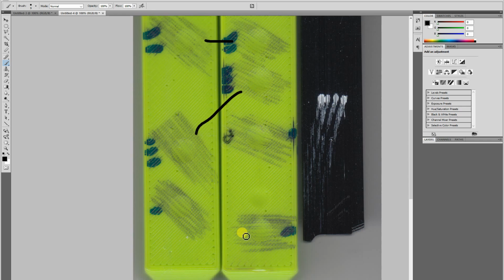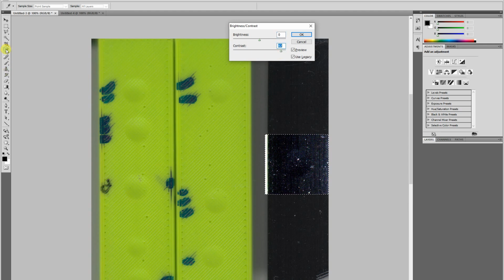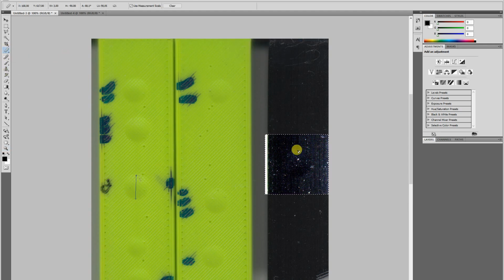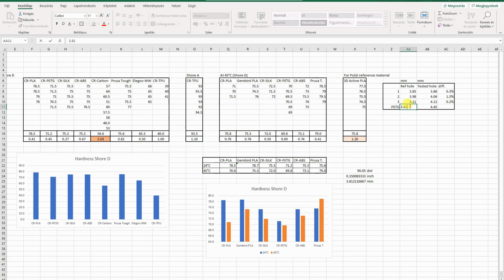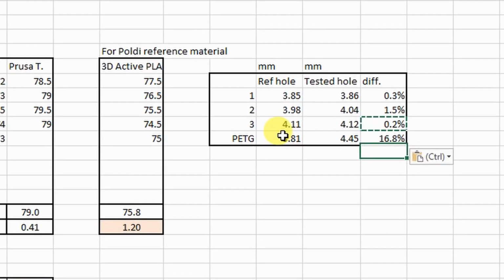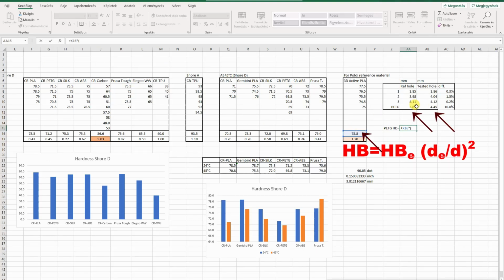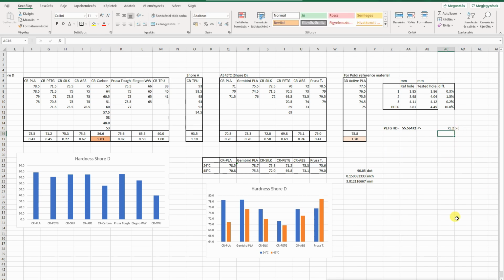So these hole pairs should be equal because they are the same materials. And the PETG hole was a little bit hard to see because of that black color, but I raised the contrast, and then I could measure this hole too. And I entered everything into this Excel table. What I noticed is that the first three hole pairs have almost equal dimensions. This is a good sign because it was tested on the same materials. But when I calculate the hardness of the PETG, I got a very different value from what I measured with the Shore Durometer. So the Poldi equation is only for Brinell hardness, and it does not work with the Shore hardness. At least not with this kind of equation.